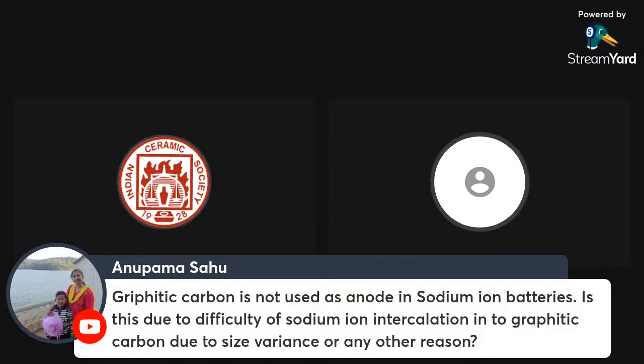Can you please confirm the question on my screen? Graphitic carbon is not usable for sodium, is it due to that? No, it is not due to the difficulty in sodium ion insertion as such. At least not related to the size of the sodium ion compared to lithium ion, which is usually thought about, because one can immediately realize that lithium ion gets intercalated, sodium ion does not get intercalated, but potassium ion can get intercalated. So it is definitely not the size.